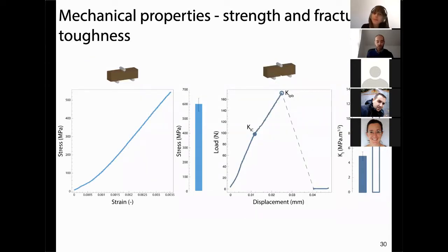So if we look at the mechanical properties, where we reach a bit higher mechanical strength, and if we look at the SENB, I'm just going to use two different values: the toughness at crack initiation and the apparent toughness when we start having this second very brutal failure. So this is all the stable part of the crack propagation.